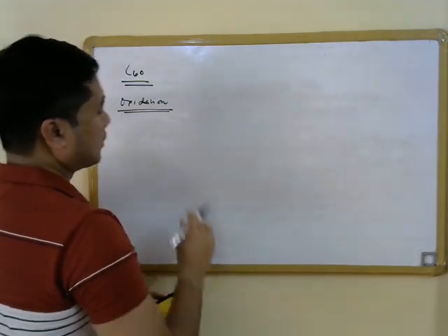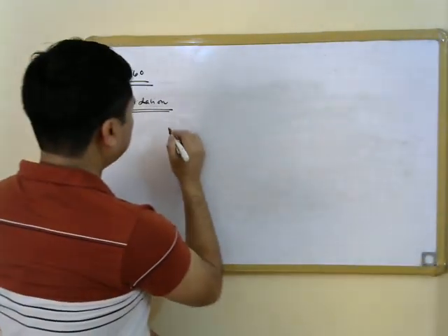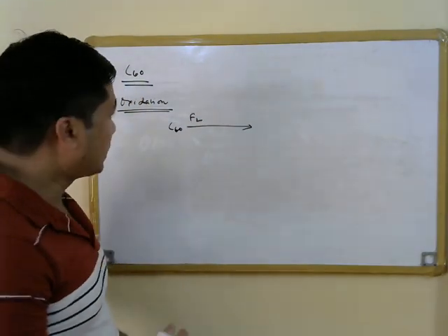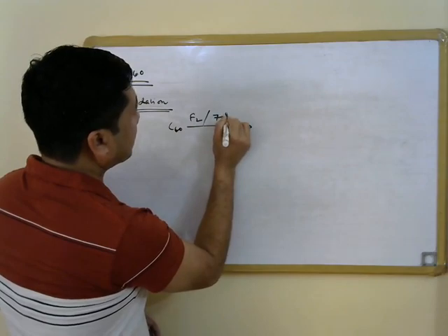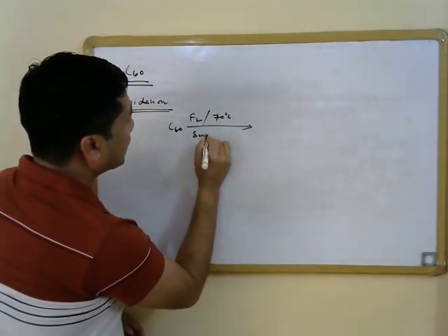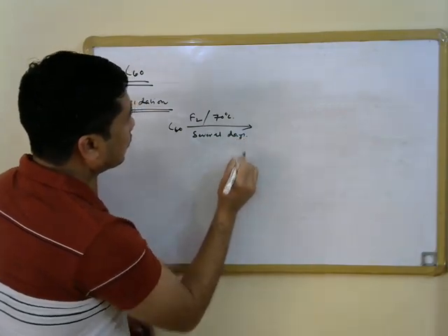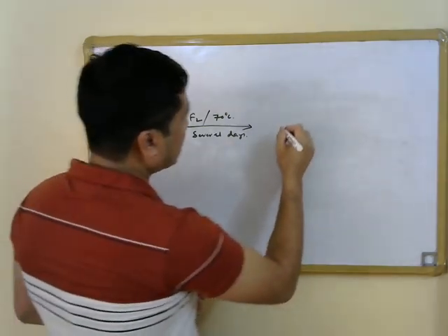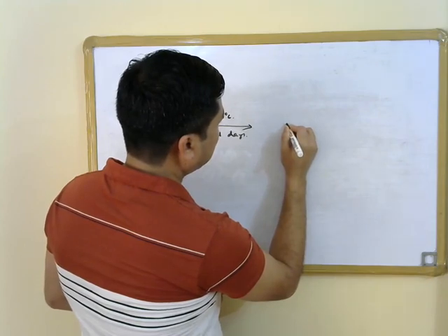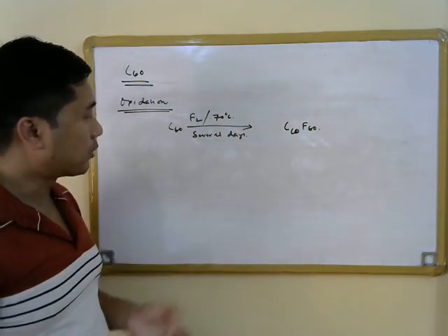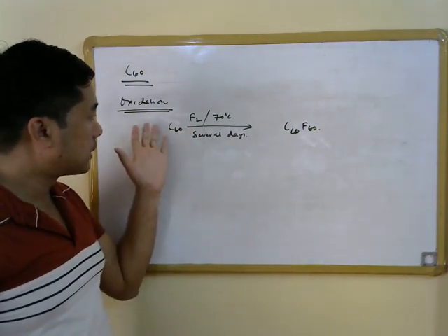Treatment of C60 with elemental fluorine at around 70 degrees Celsius for several days will fluorinate the carbon atoms, so each carbon atom essentially gets oxidized to an sp3 hybridized carbon atom instead of an sp2 hybridized carbon atom. So C60F60 is going to be formed over the course of several days when we treat C60 with fluorine at 70 degrees Celsius.